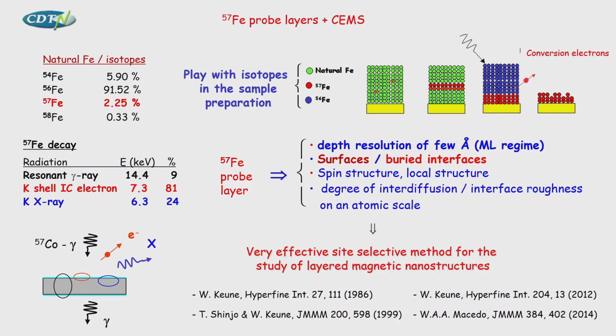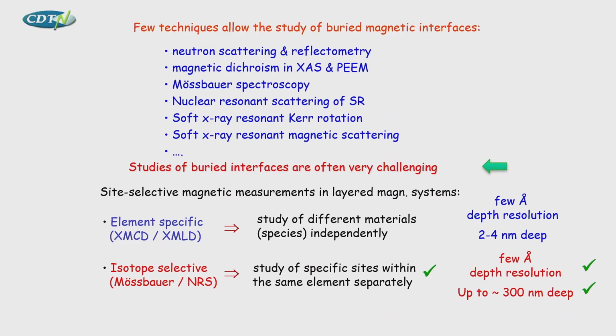That is really very effective for magnetic thin films and multilayers. And this is really very powerful because you don't have many techniques that can do that. For example, if you apply XMCD, magnetic dichroism for X-ray absorption, you can be element selective, element specific, but you don't have a big depth resolution.